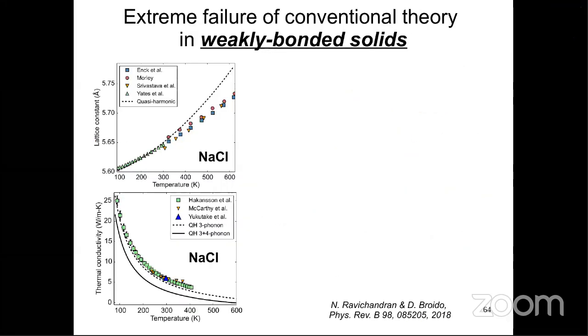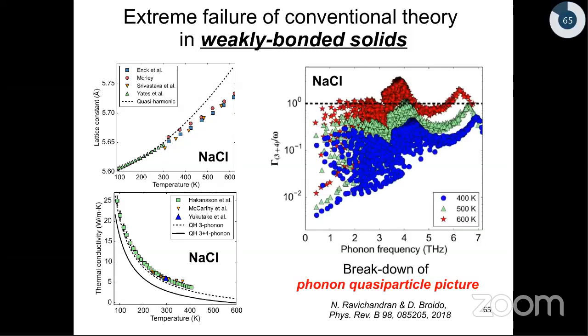I'll just take a couple of minutes to show how we are able to even capture the failures of the conventional theory for thermodynamics as well. In weakly bonded materials like sodium chloride, which is an ionic crystal, when you do the conventional quasi-harmonic approximation for the free energy, you see that the lattice constants are significantly over-predicted compared to the experiment. In the thermal conductivity also, if you do the full calculation, including 3 and 4-phonon scattering, the conductivities are much lower than the experimental measurements. And we found out, interestingly, that this failure of the conventional theory on thermodynamics is more fundamental, in the sense that the phonon quasi-particle picture is itself breaking down. For the phonon quasi-particle picture to work, gamma over omega should be much smaller than 1, gamma being the scattering rate and omega being the frequency. You can see that around 500 Kelvin, this assumption is broken down.